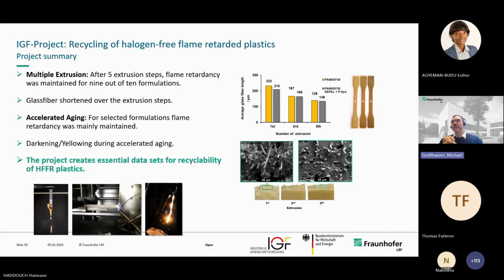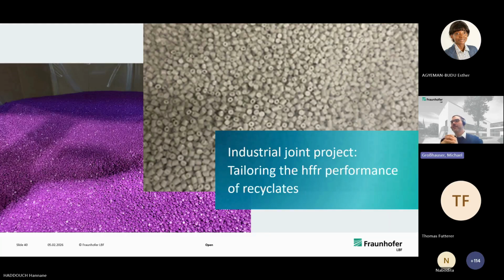And also with the accelerated aging, the flame retardancy was maintained. And what you can generally expect is the darkening. You see it also on the right side here of the material. And we used several flame retardancy testings. You see that on the bottom. And the essential data sets show that the recyclability of HFFR plastics is possible. Next slide, please. And after that, there came COVID-19.